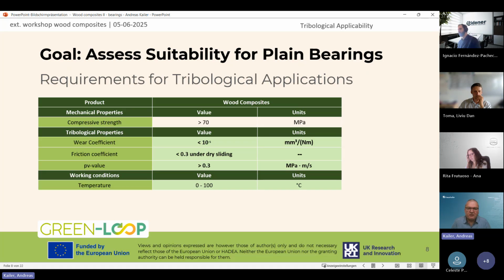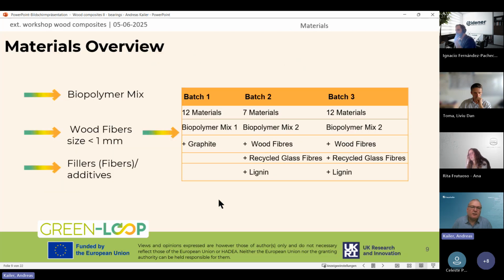So they should work within this PV value range up to 0.3 megapascals times meters per second. And temperature stability until up to 100 degrees Celsius. So these were the data we defined, the requirements.